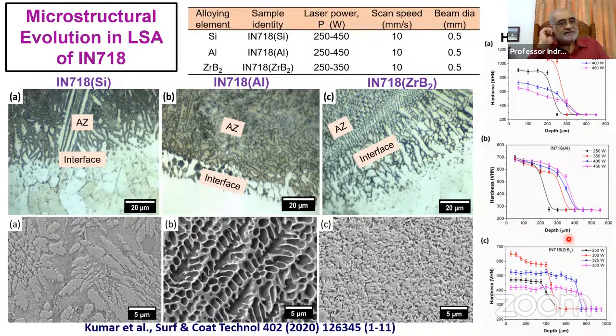But what is interesting is that Manoj actually proved that if, instead of going for oxides, you go for silicon, aluminum, or borides, then you end up making an interface which is perfectly compatible. And as you can see, some of these columnar grains are growing nicely and epitaxially from the base substrate into the very fine structure. So this is how it looks at the interface, and this is the alloy zone.